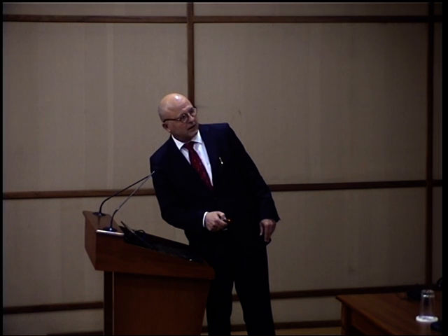The result then is very interesting. You can see here, it looks a little bit nasty, but it is very unique. It's a calcium fluoride substrate with line structures of a width of 120 nanometers. And if you calculate, from here to here is about 40 nanometers. So we can come down to magnitudes of 40 nanometers in calcium fluoride.